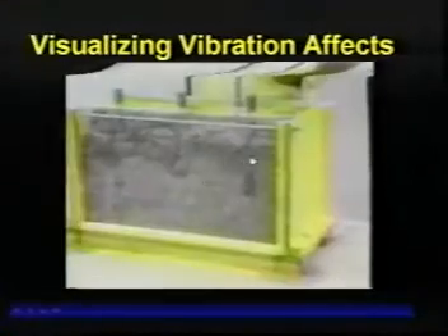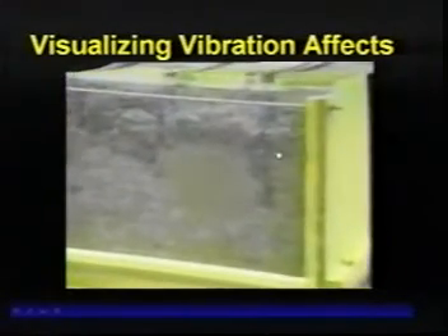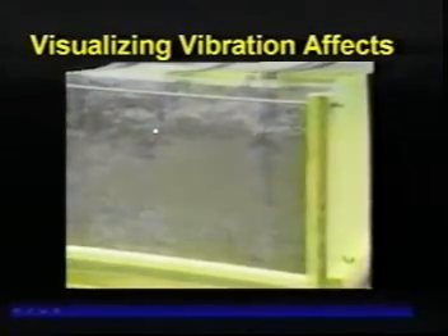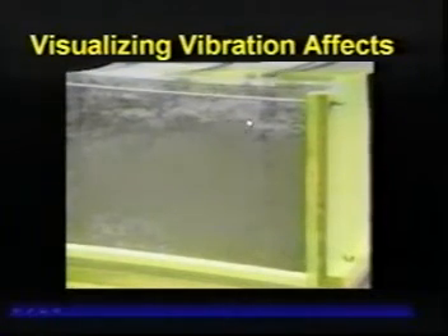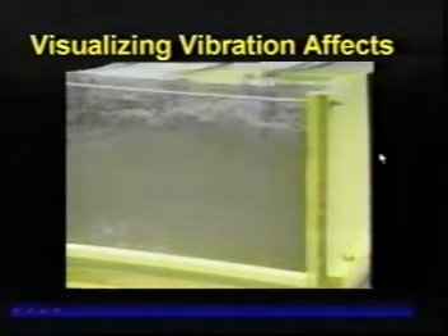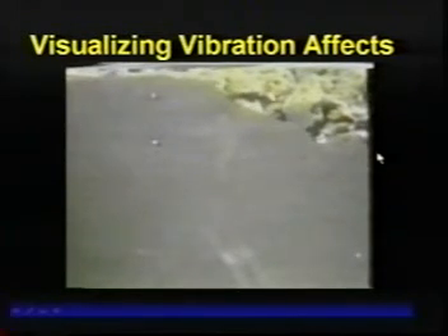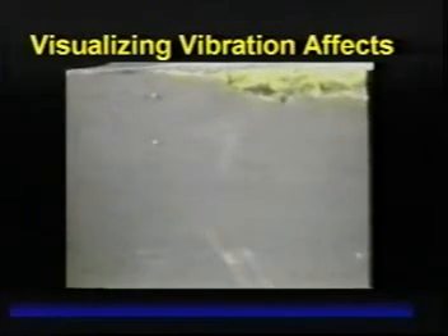Now this next video just shows the importance of that. This is a glass form on some low slump concrete. A vibrator has been inserted, and you can see how the vibrator liquefies the concrete. And we show this in training just so people can visualize this and appreciate this so they don't skip this step. Even if the repair is 3 or 4 inches thick, it's extremely important to get a good bond and encapsulate the reinforcing steel.